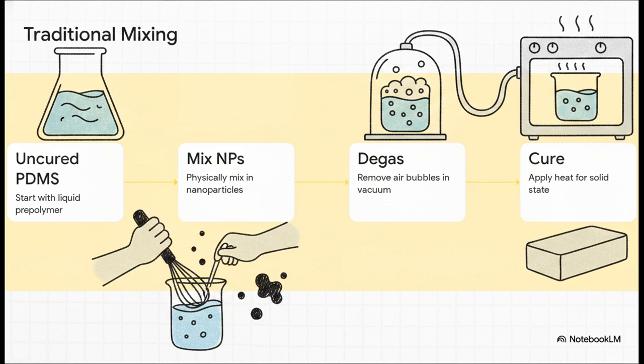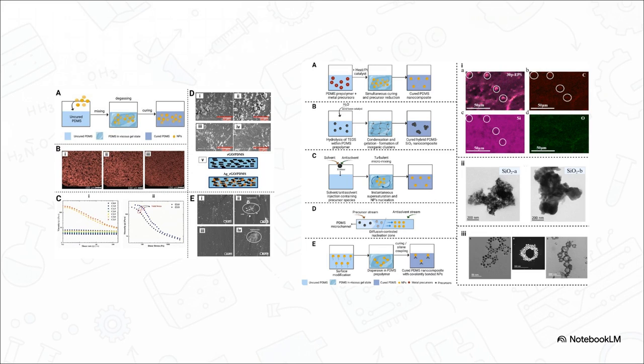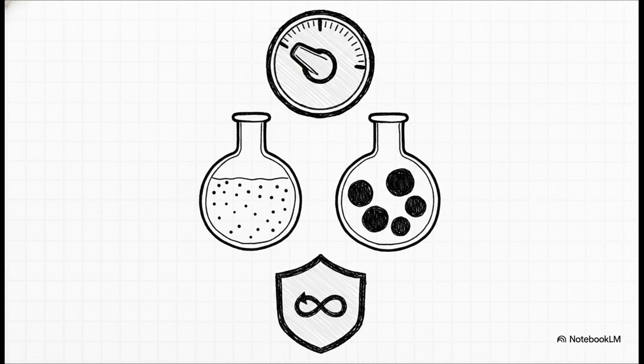It's easy and it's great for testing new recipes, but like I mentioned, physically stirring them often leads to those pesky agglomeration clumps. Now contrast that traditional mixing method with some brilliant advanced methods called in situ synthesis. Instead of mixing pre-made dust into the rubber, scientists put the chemical precursors right into the liquid rubber and actually grow the nanoparticles directly inside the PDMS matrix. As the polymer cures, the particles simultaneously form and lock into place, giving you a perfectly uniform distribution without any of the clumps.